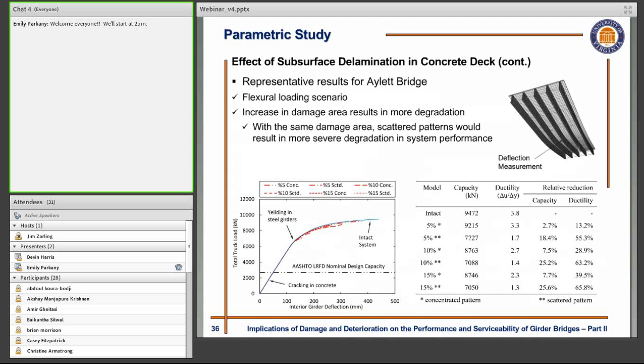In the analysis regarding the boundary conditions, we assume the same simply supported boundary conditions according to the as-built plan and design plans. For the loading scenario, we only include the flexural loading, mainly because of the location of these delaminated regions. The flexural loading will cause the worst case scenario with respect to the ultimate effect on the ultimate capacity and also ductility of the system. So we apply the load, perform the same type of analysis, and we monitor load versus deflection at midspan of the structure and compare the result for all of these 6 damage models to the intact model, which you can see in the blue lines in the following graph.